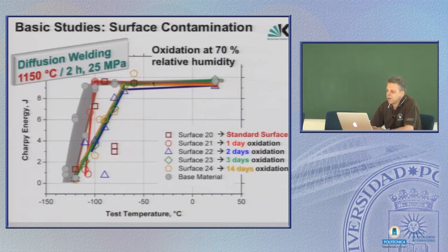And now the results are looking much more promising. There have only been slight shifts in DBTT, but not in toughness. And so in principle the results are looking quite good. What was new for me, or very interesting, after 1 day there is no effect at all. But after 2 days there is a shift of, well, 20-30 degrees or so. But then after 2 days, it doesn't matter how long you leave the material in the humid environment. It doesn't matter whether 2 days or 2 weeks. So this is also interesting information regarding industrial fabrication. You can produce the surfaces, and if you don't mind a shift of 30 degrees C in DBTT, you could store the prefabricated plates for weeks without any consequences.